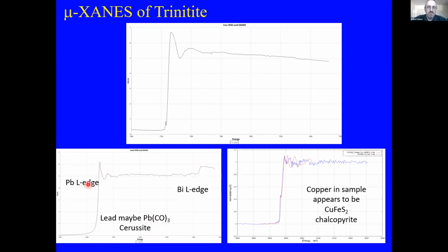But in other points on the spectra, we didn't see any bismuth. So our theory at the moment is that the samples which have no bismuth were closer to the fireball than the samples that do, because bismuth has a lower boiling point than lead. The copper appears to be chalcopyrite, which is the naturally occurring mineral for copper in the Nevada desert.